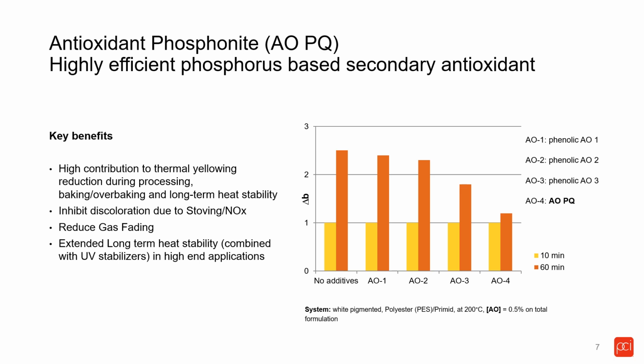Even within the phenolic ones, you have quite a choice. However, they don't perform the same, and that's what we see in these evaluations. We have the contribution to the yellowing. The Y axis here is delta B, which correlates to the yellowing of the coatings. The coating used in this study is a white pigmented polyester primid system, cured at 200 degrees Celsius, and we use 0.5% of the antioxidant in this experiment.